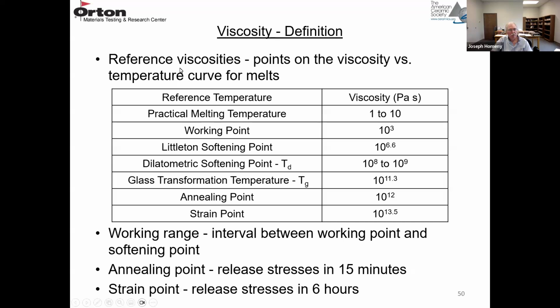So these are reference viscosities. These are points on the viscosity versus temperature curve. So this is your reference temperature. This is your viscosity, in Pascal seconds. So at the melting temperature, the viscosity is going to be between 1 to 10. The working point, where you can form a glass into some useful object, is about 10 to the 3.